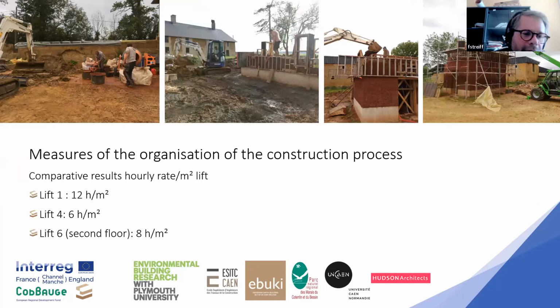We measured a lot of things during the building process. We tried to measure the organization of the building process, of the construction. So here are samples of the time of implementation that we measured, showing that for the first layer we spent 12 hours per square meter, and then for the fourth lift, just using the digger, we managed to reduce this time of implementation by 2.